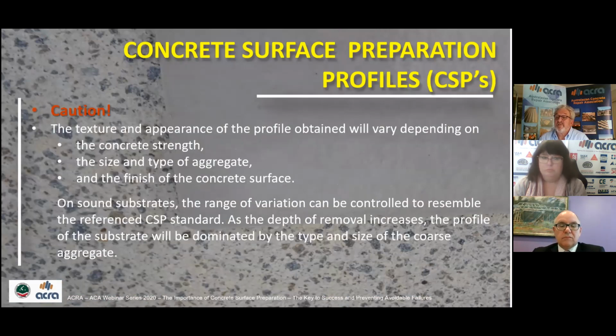There is a caution note that the texture and appearance of the profile may vary depending on the concrete strength, the size and type of the aggregate, and the finish of the concrete surface. On sound substrate, the range of variation is significantly controlled to resemble the reference standard. As depth of removal increases, the profile of the prepared substrate will be increasingly dominated by the type and size of the coarse aggregate within the concrete.